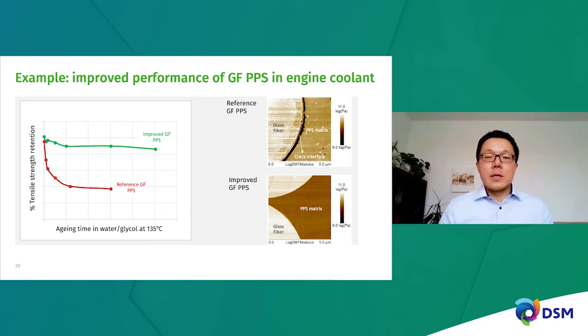And if you look into the AFM figure or SEM figure, what you see in the right-hand side figure there is that for the reference GF PPS, as I said before, after a certain period of aging time, you see a debonding, whereas for the improved glass-filled PPS, you don't see any debonding, and it is translated to the increased tensile strength retention.